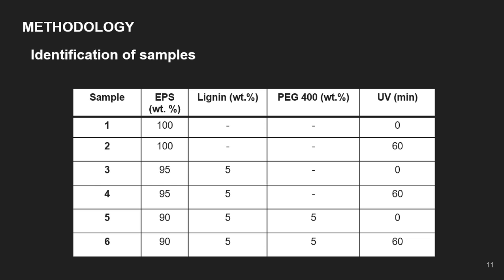As a final product, 6 samples were obtained, 1 and 2 of which are pure EPS films, 3 and 4 EPS with 5% lignin, 5 and 6 EPS with 5% lignin and PEG-400 plasticizer. Also, samples 1, 3, and 5 were not submitted to photochemical treatment, while samples 2, 4, and 6 were exposed for 60 minutes to UV radiation.